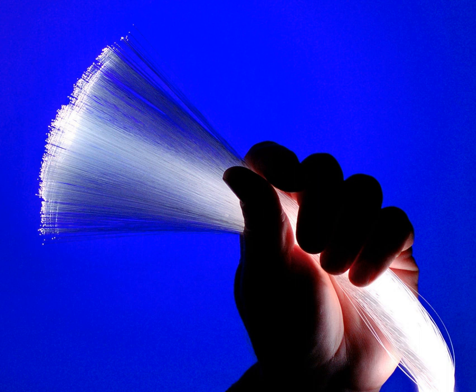Today's glass optical fiber draw processes employ a dual-layer coating approach. An inner primary coating is designed to act as a shock absorber to minimize attenuation caused by micro-bending. An outer secondary coating protects the primary coating against mechanical damage and acts as a barrier to lateral forces, and may be colored to differentiate strands in bundled cable constructions. These fiber-optic coating layers are applied during the fiber draw, at speeds approaching 100 km per hour. Fiber-optic coatings are applied using one of two methods, wet-on-dry and wet-on-wet. In wet-on-dry, the fiber passes through a primary coating application, which is then UV-cured, then through the secondary coating application, which is subsequently cured. In wet-on-wet, the fiber passes through both the primary and secondary coating applications, then goes to UV-curing. Fiber-optic coatings are applied in concentric layers to prevent damage to the fiber during the drawing application and to maximize fiber strength and micro-bend resistance.